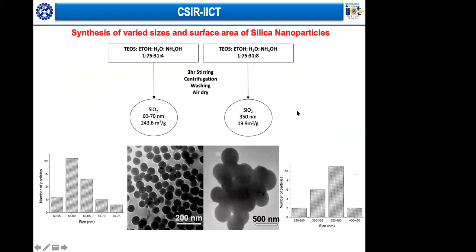Then we had to see the influence of the size on this catalytic reaction. So we looked at their surface area, which plays a major role when we are using these materials as catalysts. These 60 to 70 nanometer silica nanoparticles have a surface area of about 240 square meters per gram, whereas the 350 nanometer particles have 20 square meters per gram. So the surface area comes down drastically when the size is increased to 350 nanometers. Obviously, the particles of 60 to 70 nanometers are better catalysts and give a better yield compared to the 350 nanometer particles. That's how we looked at the influence of size on the catalytic activity.